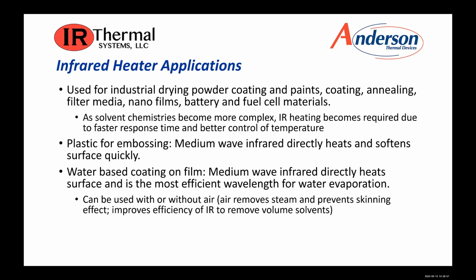And for plastic for embossing, medium wave infrared directly heats and softens the surface quickly. And for water-based coatings on film, medium wave infrared directly heats the surface and is the most efficient wavelength for water evaporation and can be used with or without air. Air removes the steam and prevents skinning effect. Improves efficiency of IR to remove volume solvents.